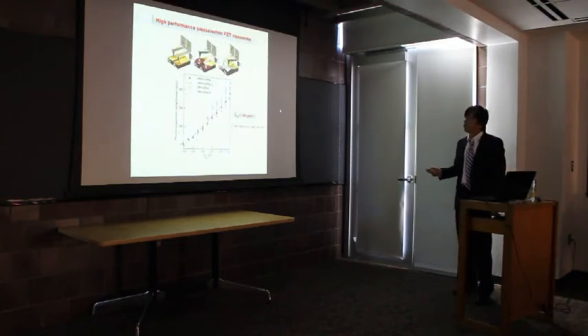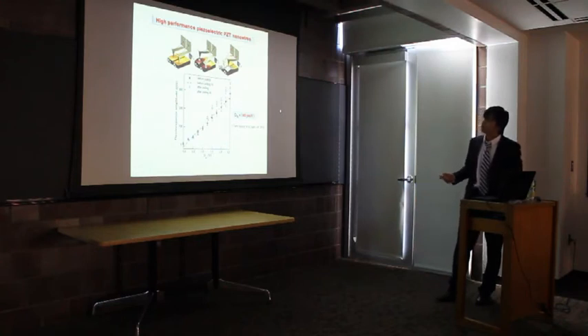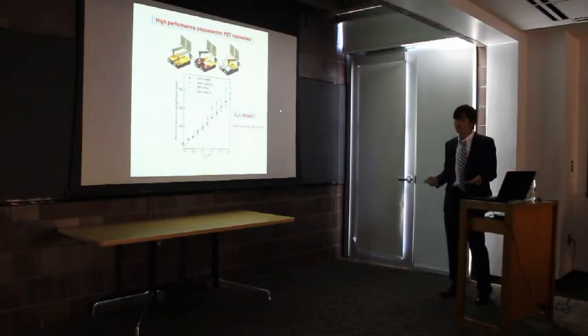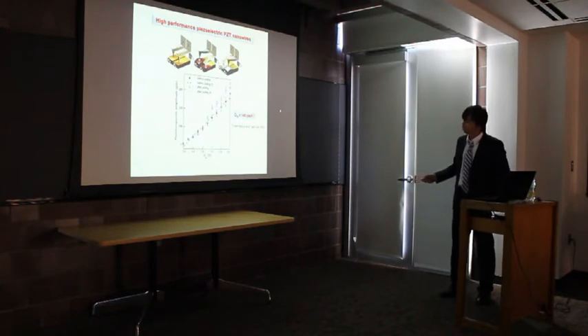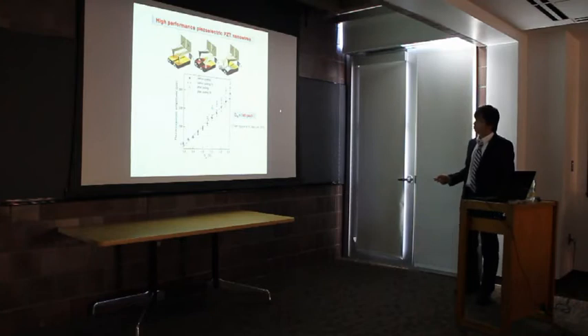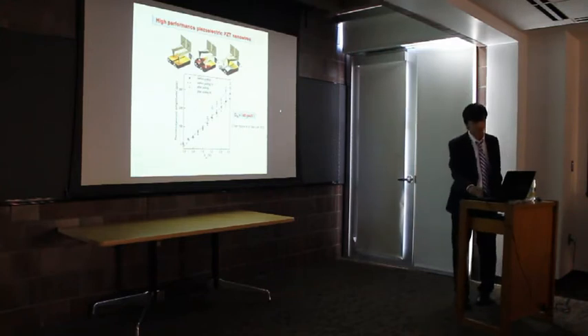But most importantly, we measured the piezoelectric constant in the PZT nanomaterial. The way we did that was with PFM, which stands for piezoresponse force microscopy, a modified AFM in which the tip is conducting. We apply AC voltage between the tip and the bottom and get the deformation at the same frequency via the lock-in amplifier. When we increase the AC amplitude, we get an increase in the deformation. And the d33 we get is about 140 picometers per volt. At the time I published this paper, this was the highest d33 of piezoelectric nanomaterials. So it's a really wonderful result.